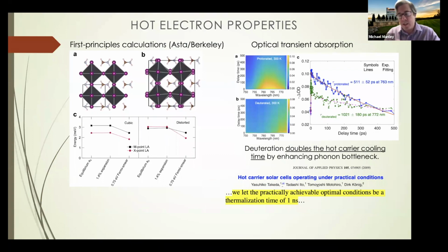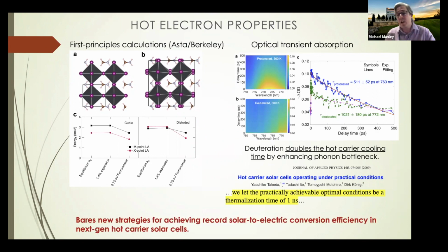And with that, they said, well, maybe we can get 50 to 55% efficiency. But I don't want to say that we're going to. Like I said before, the whole point of this is to understand how to control the thermal transport, not necessarily to make material specifically this way. Because now we can look at, say, you change the molecule in such a way, chemically, you could maybe make a change that moves the band gap the way you want, or something else. And you also want to look at, oh, maybe we can gain something on the carrier lifetime. So that's the idea. And it really is, it bears new strategies for achieving conversion efficiency. Okay, so that's the main point of the first part.